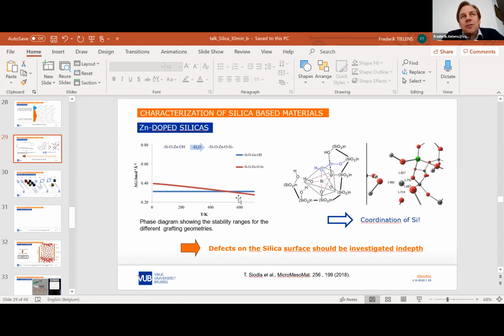In fact, it's nothing more than a linear function, which is corrected by the entropy of water. You put T as a variable, the temperature, and then you obtain these lines that cross at a certain temperature. But we have not done molecular dynamics simulations for this. The temperature is only an approximation, or better, an extrapolation of some punctual calculations. I see. Okay, I have a few more questions, but unfortunately we won't have time, right? So I will turn off. Thank you very much.